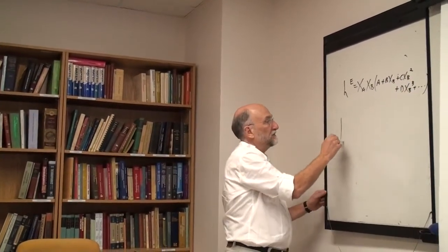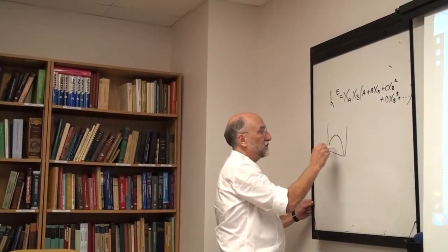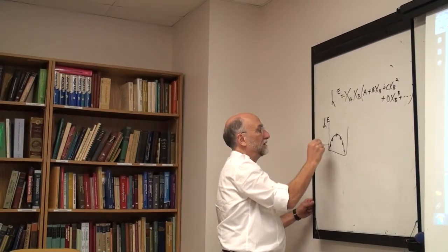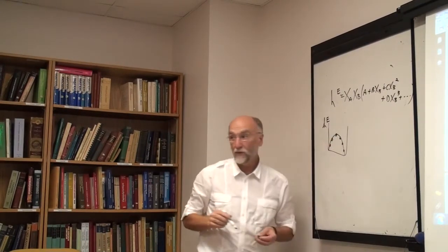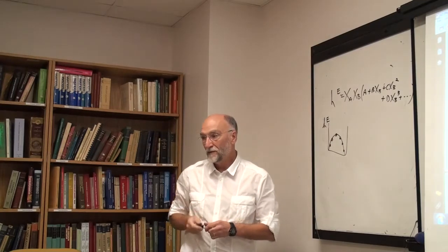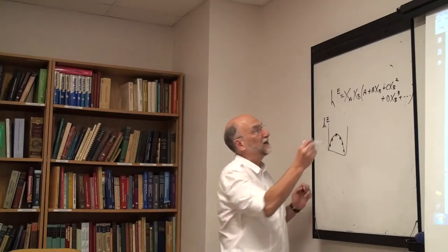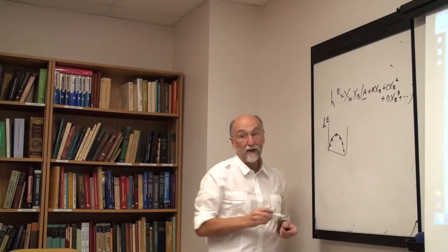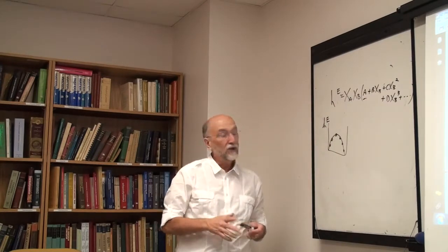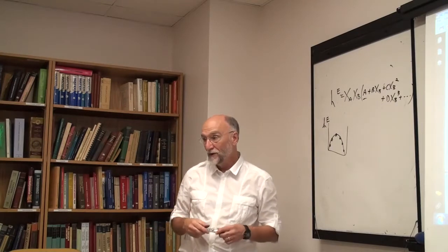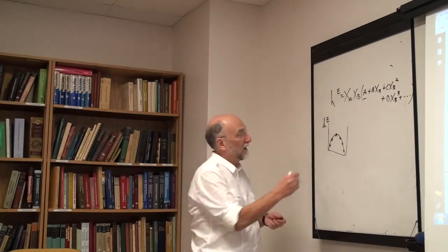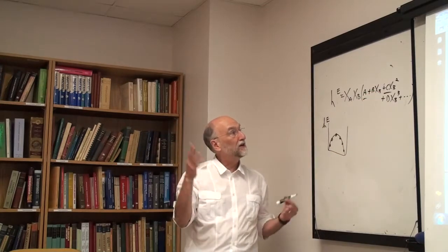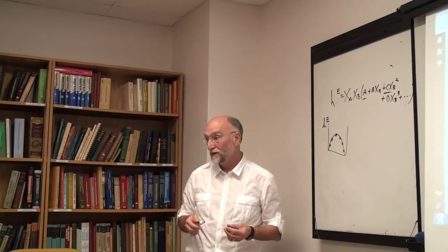And let's say I have experimental points here of H^XS, and I'm trying to fit those points to a curve. What's happening? Say I try to do a fit with one coefficient, which of course gives me a symmetrical curve, so I find it doesn't fit too well. I need two terms. I add two terms, it fits a bit better. I add three terms, it fits a little bit better, and I go on. I find I need 4 or 5 terms to fit the thing properly.